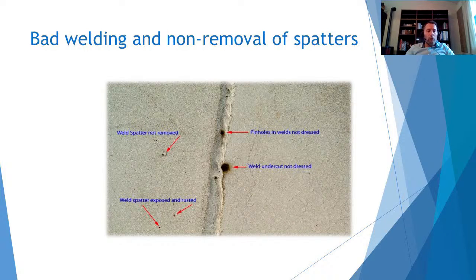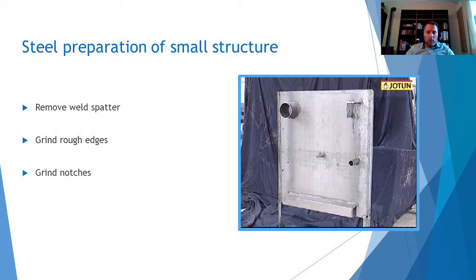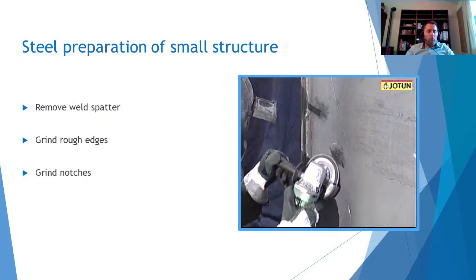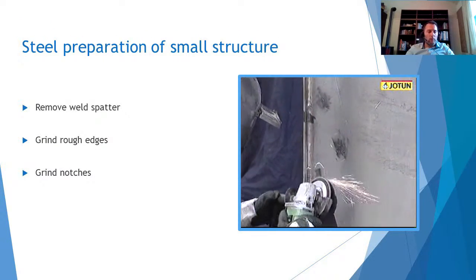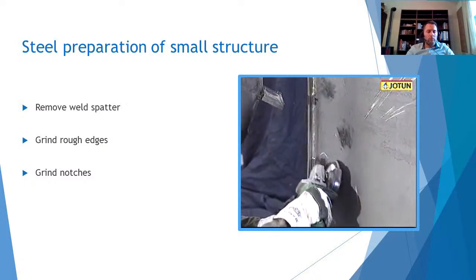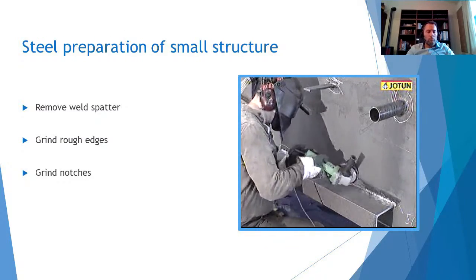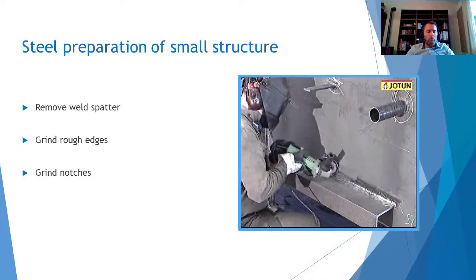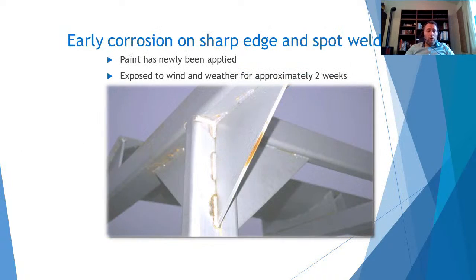In this picture, we see a steel preparation of a small structure. In this case, we are talking about a CPT, control panel test, according to standard NORSOK M-501 revision 6. So the process is to remove weld spatter, round the edges, and grind the notch. Early corrosion on a sharp edge and spot weld.